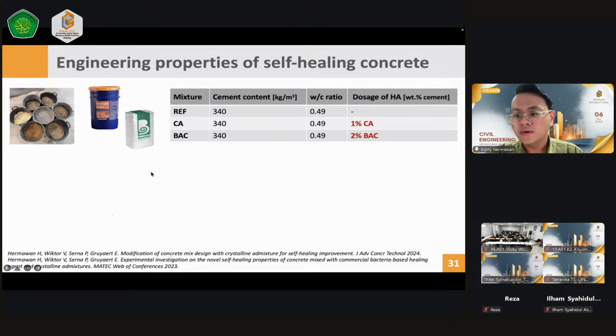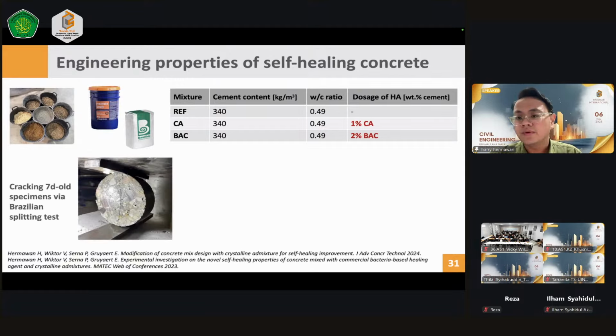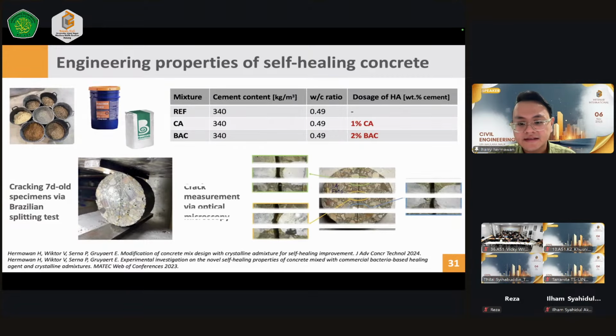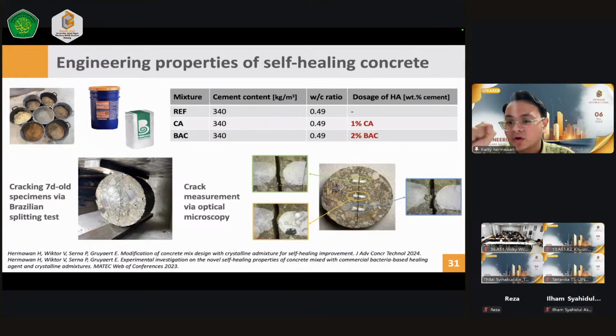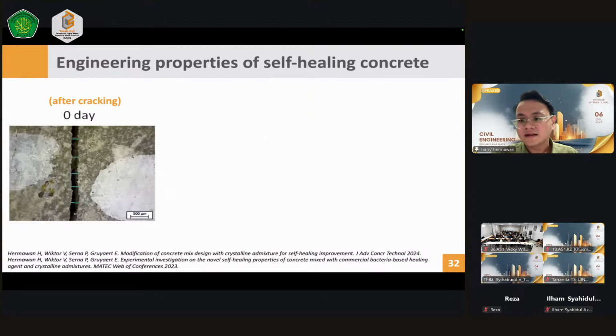And then what should I do with this specimen later on? First of all, we can crack our specimen via the test called the Brazilian splitting test, which is the one that I showed before. After the concrete experiences any cracks, we can make some marks on our cracks, and then use optical microscopy in order to check the width of the cracks. Let's have a look. After cracking, we can see from the picture that there is no healing activity, because the concrete was just cracked at the time.